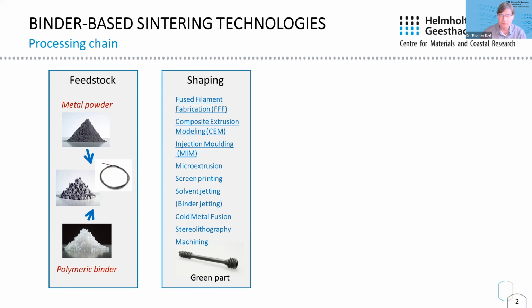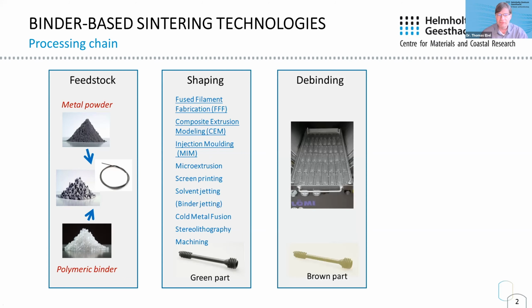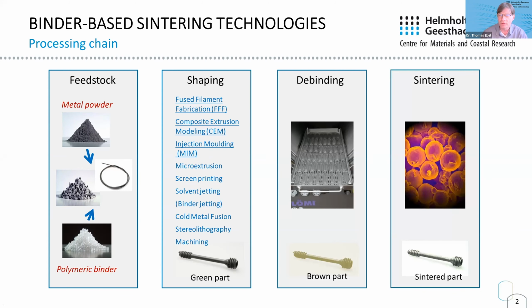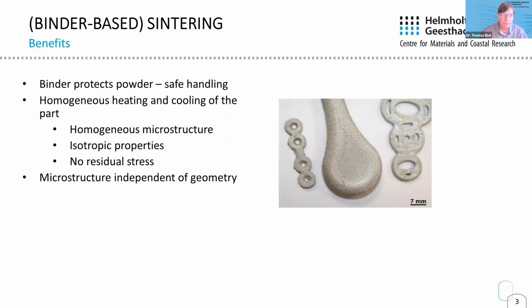Independent of the technology you use for shaping, you need, after the shaping process, a debinding step. So that means you remove the binder. Usually it's a two-step process, one solvent debinding and then a thermal debinding prior to sintering. And after sintering, you have the part which is ready to use. One real benefit of this processing is that the binder protects the powder. So this feedstock you can handle very easily. It's a safe handling you get.